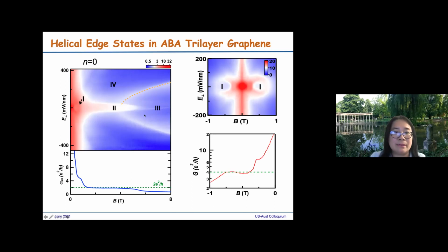Now you can also see that both phase three and phase four are insulating. But the two blue regions are separated by a white line, which shows that the conductivity temporarily goes up at that line before dropping again. So even two different insulators are connected by a conductive region, which suggests that these two insulators have different symmetries, and so the transition between them is not continuous.